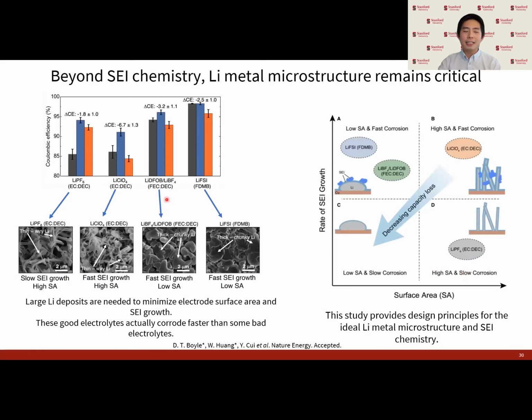Among the good cycling electrolytes, we can see that they have low surface areas of lithium deposition, but very fast corrosion kinetics. But what we really need to make lithium metal anodes more viable are lithium metal chemistries that have low surface areas and slow corrosion kinetics, in addition to having good cycling stabilities.